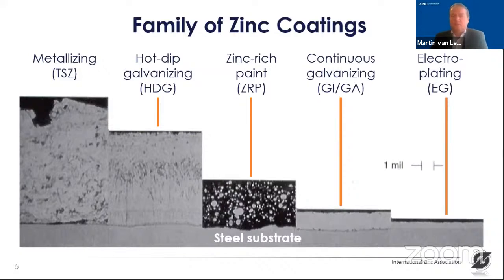The fourth category is continuous galvanizing, which is used for galvanizing sheet or different kind of applications. You can find it in automotive or in white goods or in construction. And depending on the end application, you can apply a thinner or a thicker coating. The coating thicknesses typically range from 10 to 30 or 35 micrometers. And the last category here is electrogalvanizing or electroplating, which is typically used for automotive steels with a coating thickness of maximum 10 micrometers.